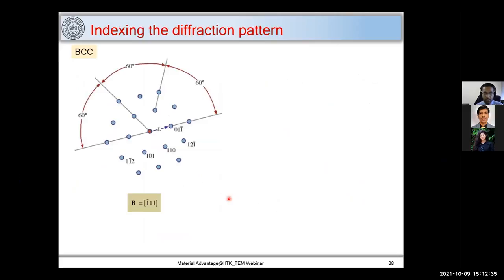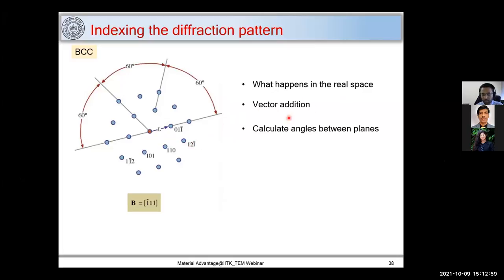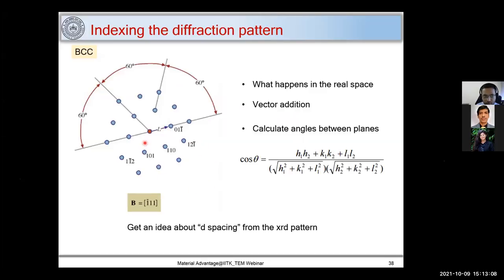Now, coming to indexing a pattern, you should always know what happens in real space. Imagine a crystal structure and try to find out how it gives you a diffraction pattern. Here you can use vector addition. Let's say I have 0, 1, bar 1 and 1, 1, 0; I can add these two and get 1, 2, bar 1. You can calculate angles between planes, and you can find the cos theta between these two planes also. This is simple for a simple BCC structure. You should get an idea about the d-spacing from the XRD pattern. I'll be dealing with it shortly.